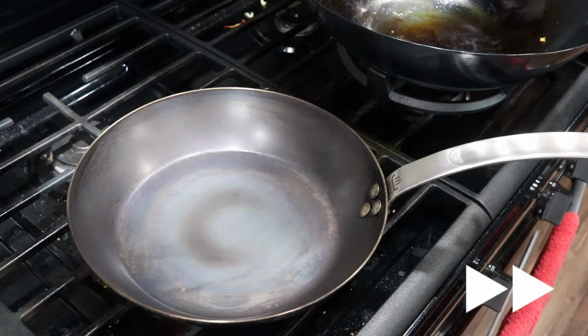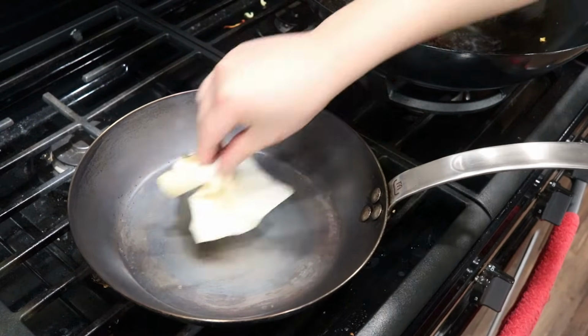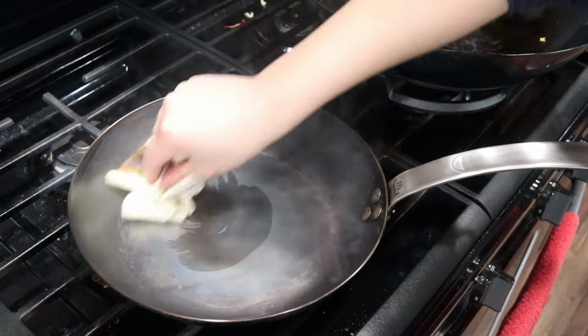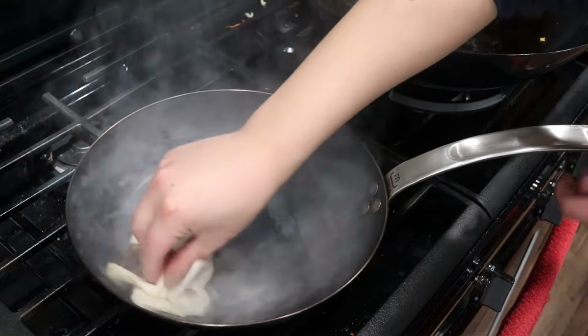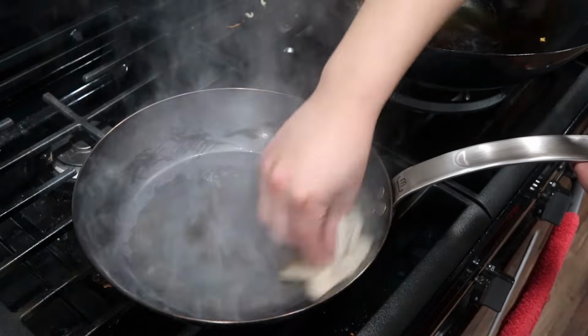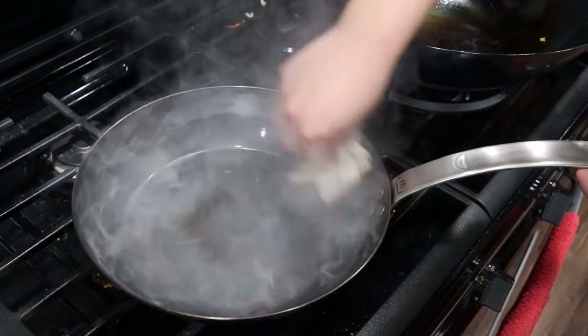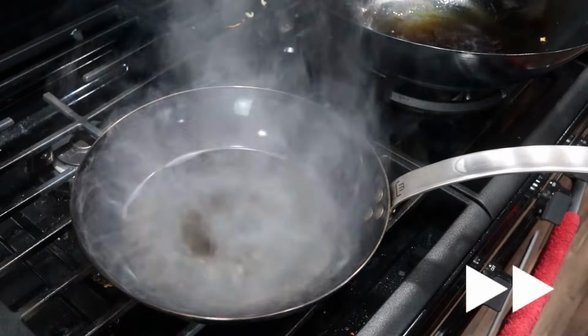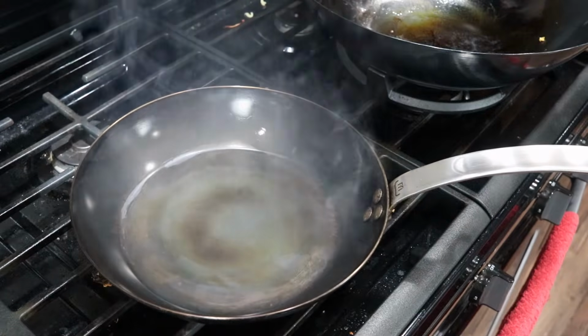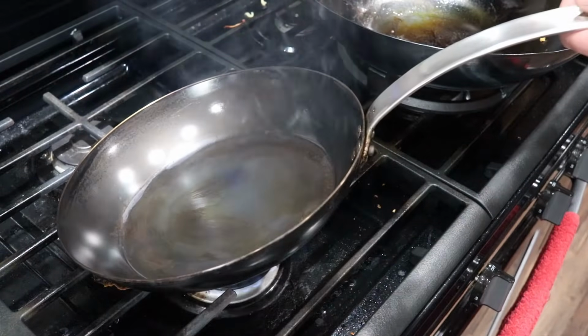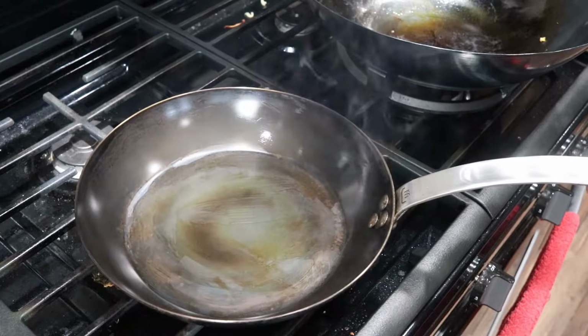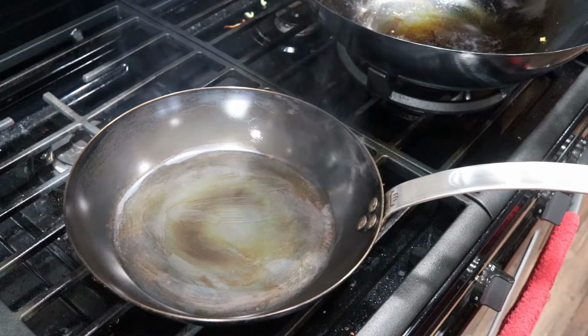Anyways, after the bluing is done and the pan has cooled down a bit, use a paper towel, dip it in some high smoking point cooking oil such as canola or peanut. Give the cooking surface of the pan a very light coating of oil, then heat up the pan over a medium heat until the oil starts polymerizing. Let the pan cool down a bit before adding more layers of oil for seasoning. I usually do about 3 to 4 layers and call it good.